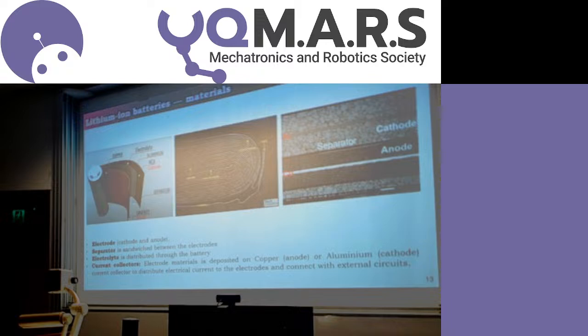What can cause the thermal instability in the first place? So you can get local destabilization if you just have an imperfection, and you might get a small little mound in one section. It's slightly closer. It might be gradual in that you might gradually get higher and higher current going through an imperfection in your electrodes. So you have current density distribution inhomogeneities in the system, and then it gets amplified over time. So that could be one thing.